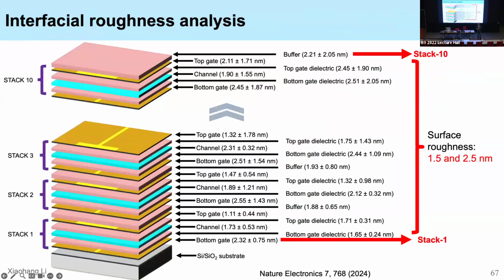So one of the key things for the stacked transistor is the interfacial roughness. Electrons are very demanding nanoparticles. They only want to run on a very smooth highway. They do not want to operate on a bumpy road, right? So ideally, you want to have your interfacial roughness less than 5 nanometers, so that electrons can move very efficiently without being scattered. If you look from stack 1 to stack 10, at stack 1 we have a roughness of about 1 to 2 nanometers or so, right? Which is actually quite good. And if you move up, at stack number 10, we have a roughness of about 2 nanometers, which is still quite acceptable. So I believe that if we continue to stack more transistors, we can actually shoot for an even larger number of stacks.